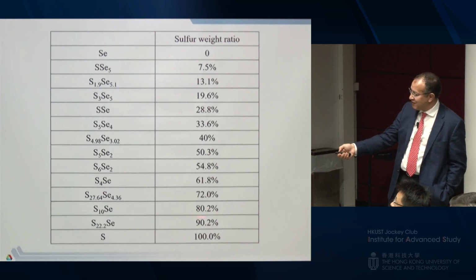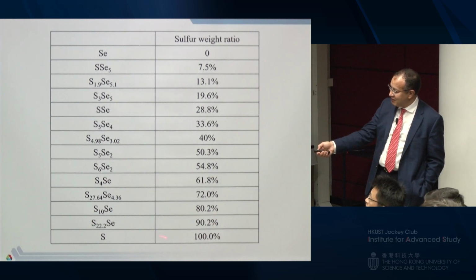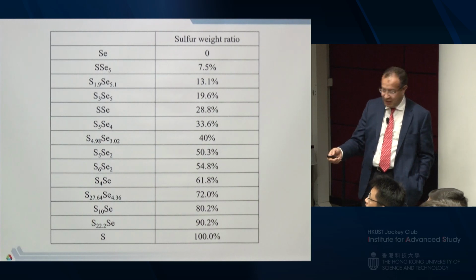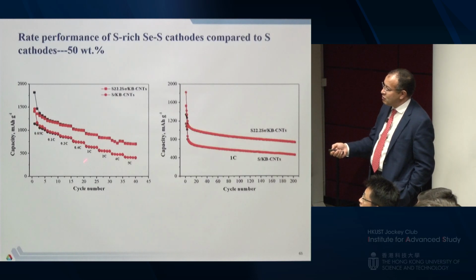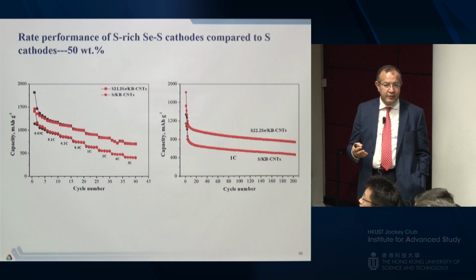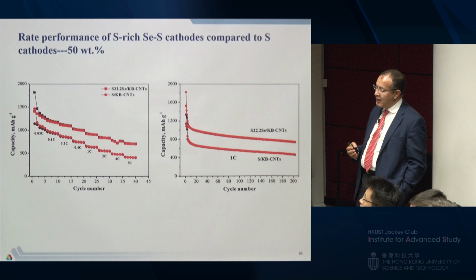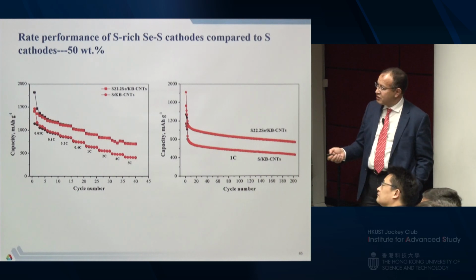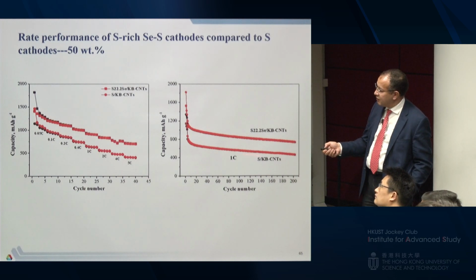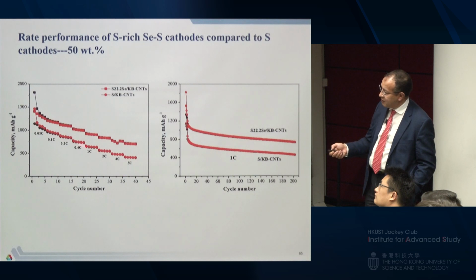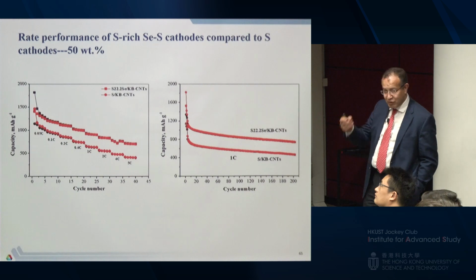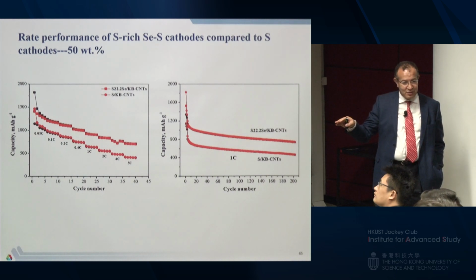You're almost close to sulfur, 90% versus sulfur. So capacity-wise, almost similar. And this is what we got, because here we are able to put a high concentration or high ratio of active material, almost 80% versus 50% for sulfur, and we operate at 1C rate and a different rate. You can see clearly that this new system outperforms sulfur better without dissolution.